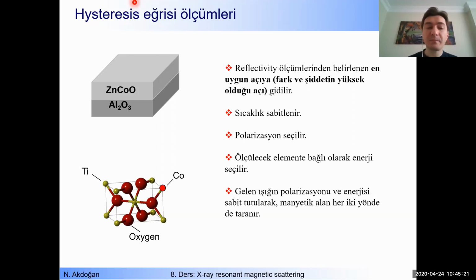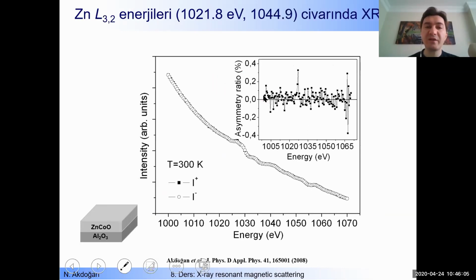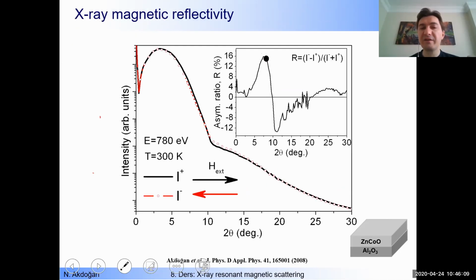For example, if you would like to use this type of material as a permanent magnet, then we need high coercive fields, okay? And we need hard magnets. But if you would like to use that type of material in magnetic sensors, then we need low coercive fields. We need soft magnets. So hysteresis curves can give that information about the magnetic materials. So how do we carry out hysteresis curve measurements by using the XRMS method? First of all, we go to the best angle, which we determined from the reflectivity curve. Here we carried out reflectivity curves and then determined the best angle, where the intensity and the magnetic difference are maximum.